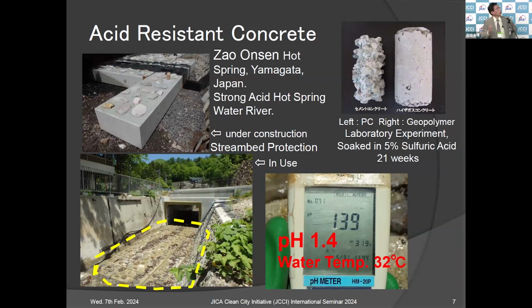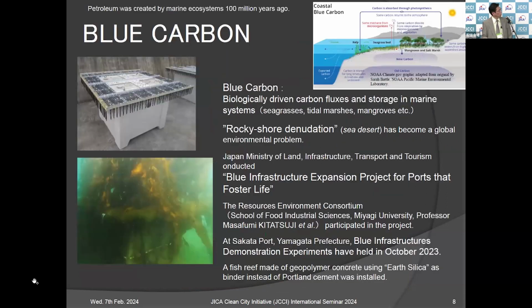Now, changing gears, the geopolymer concrete is resistant against acid. This is an example from Japan. This is in Zao Onsen Hot Springs in Yamagata Prefecture of Japan, where the water is very strongly acidic at a pH 1.4, and we're talking about thousands of liters of this acidic water, and that water goes into the river, and we in fact applied this material to the stream bed protection underneath the bridge. And at the right top, you can see the cement concrete being compared against the geopolymer on the right, exposed against a very sulfuric solution. And so you can see Hydegas concrete is very strong. Geopolymer is strong against acid.